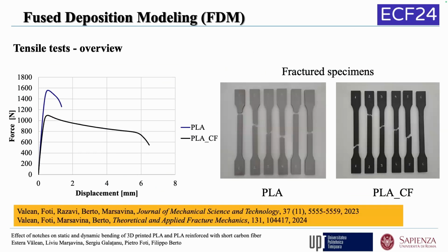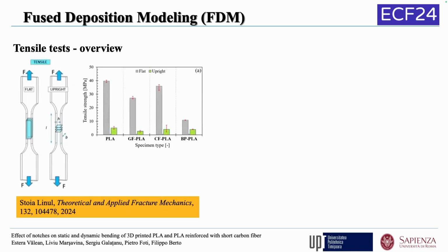Nowadays, this technique is used more and more in different industries. Up to now, there are some studies published regarding the tensile results on PLA and PLA reinforced with carbon fiber. So we did some tensile tests, and what we get is higher strength, but also higher tensile modulus for the PLA compared with PLA reinforced with carbon fiber. I was looking in the literature, and there are other authors who get the same results.